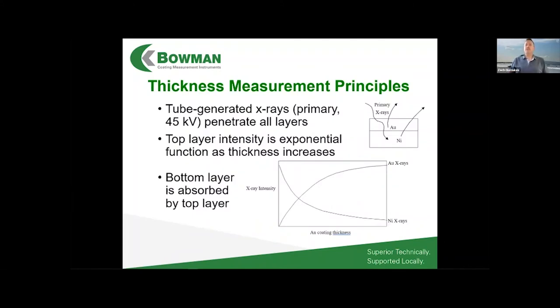So the basic principles of how we measure the coating thickness is, like any XRF, we have an X-ray tube that's generating the primary X-rays. We're typically running our tube, and again, I'll get more into the hardware, at a 45 kV energy range. And so that's enough energy to typically get through all the different layers that we're working with. Whatever layer's on top, like if you look in this simple little diagram, I've got gold plated over nickel in sort of a schematic here. So the top layer of gold in this case, that intensity is going to be the strongest because it's the X-rays that are coming out of the surface.